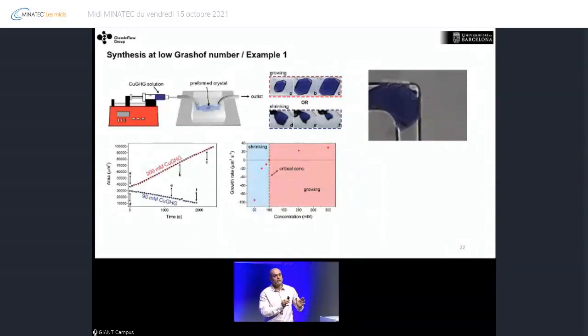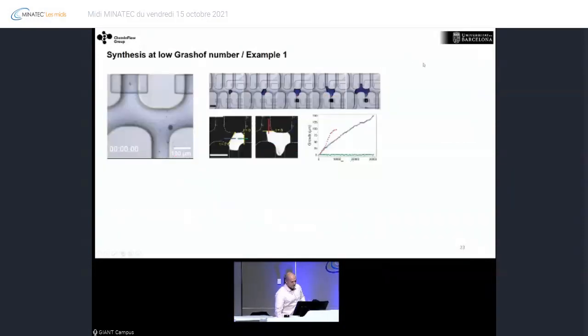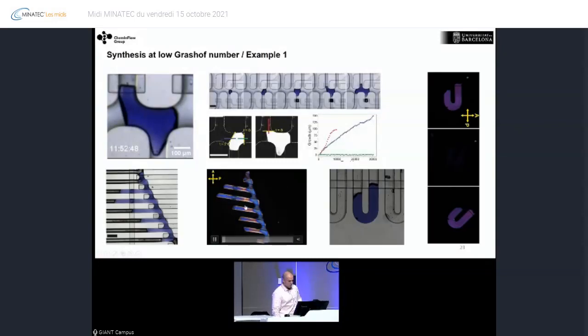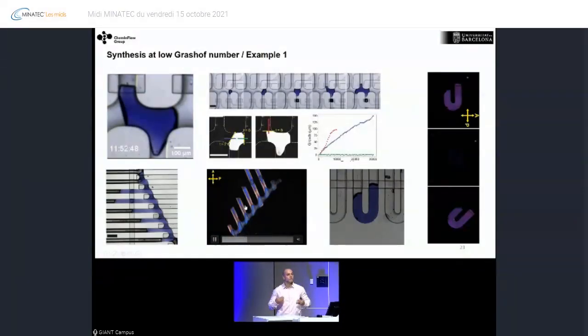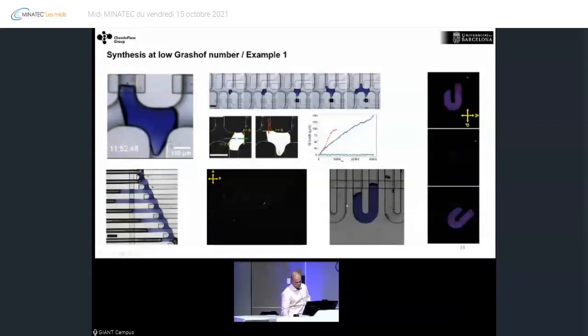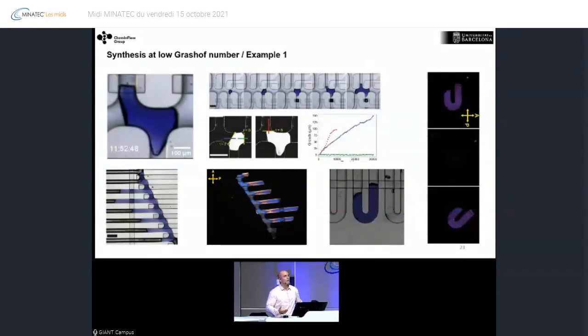Here, in these conditions, in these free interface diffusion processes, we are able to keep the system always out of equilibrium, because we are constantly adding mass to the crystal. So what this allows us to do is, if we add new nutrient here, we will accelerate the growth of the crystal. By doing so, we can make very complex structures with these MOF crystals. As you can see also here, this is a single crystal, and of course, this is a shape that you will not be able to generate in conventional laboratory conditions.